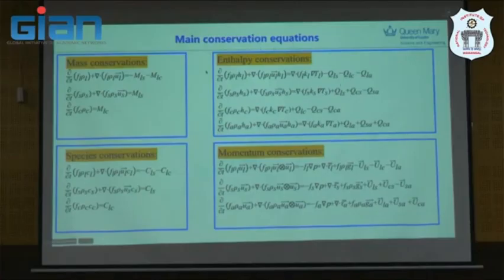We can see that the mass transfer only occurs in the liquid phase, equiaxed grain, and columnar phase. And the interfacial transfer exists between all these four phases.